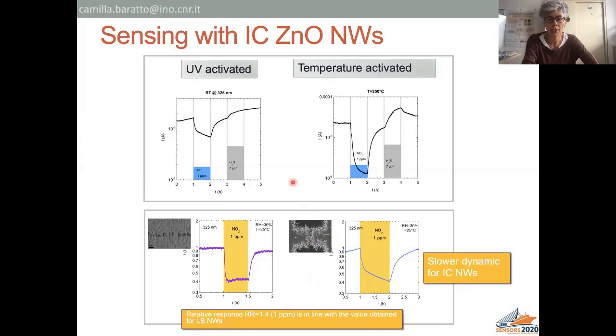If we consider for this type of sensor UV activated compared to temperature activated sensor, for UV activated we have detection of oxidizing gases, while no detection of H2S was observed. In this case, at 290 degrees, we still have detection of NO2 with also some detection of H2S.